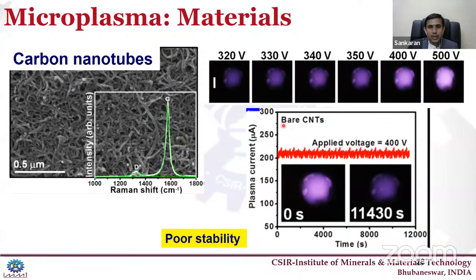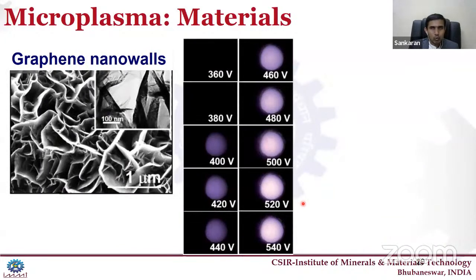And you can see the bare carbon nanotubes, even at 400 volt, show only a very short lifetime, and the plasma intensity is getting less as compared to the 0 second. So the carbon nanotubes have poor stability. And we also tried with the carbon nanowalls. We tried a graphene film with a thickness of between 10 and 20 nanometer, but within a second it was etched out. Once the plasma emits, the graphene was completely etched out by the plasma.